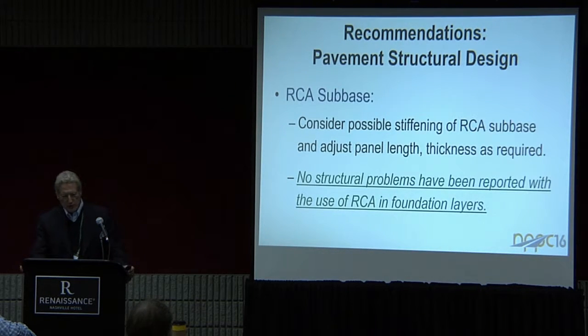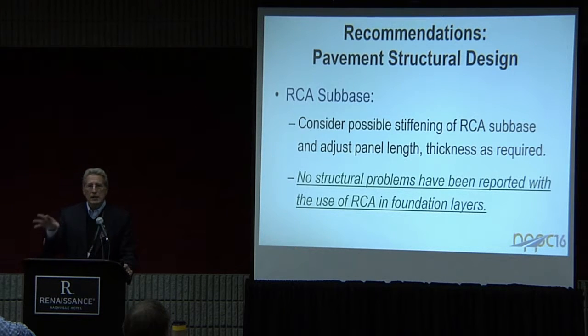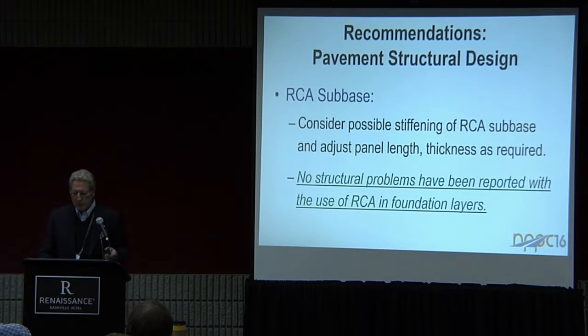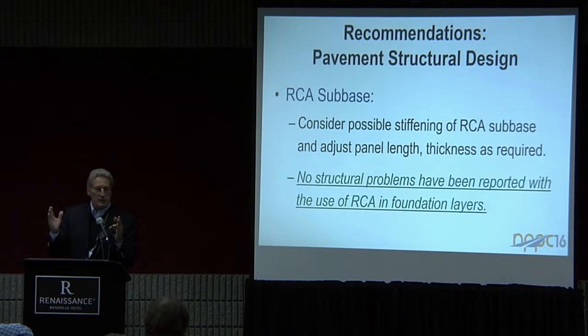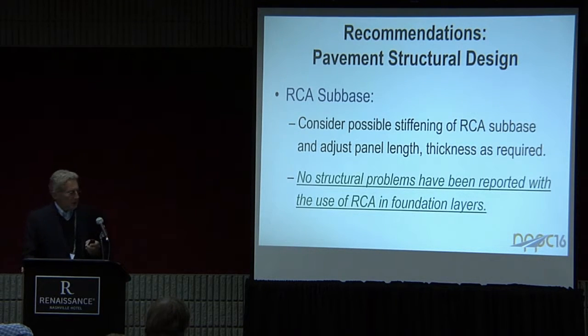In terms of structural design, the fact that the material will stiffen in that subbase can be a good thing in terms of having reduced thickness requirements on top, but it's also something we need to keep an eye on. If you have a stiffer subbase and you're building a concrete pavement on top of it, your curling and warping stresses tend to increase, and your frictional stresses between the slab and the foundation may be a bit higher. And those may necessitate that you adjust the thickness of the pavement accordingly, or maybe you're going to shorten up your joint spacing to reduce your curling and warping stresses. So it's always something to take a look at.